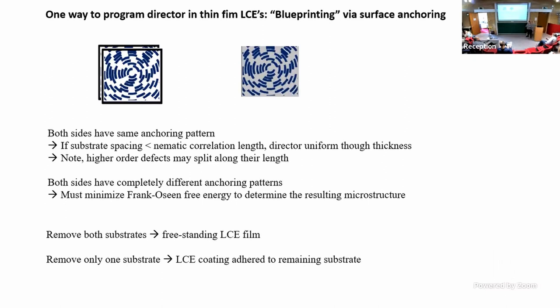Another key issue is that there is a nematic correlation length. So there's a limit to how far I can put those two pieces of glass apart to really have a pattern that cuts all the way through the material. If we want something thicker than that, another option is 3D printing. And there's a couple different ways to do that. So what are the numbers, typically on top of the millimeter? Microns. Only microns? Microns. Because the nematic correlation length is not that long. But if you 3D print, you can make it as big as you want.